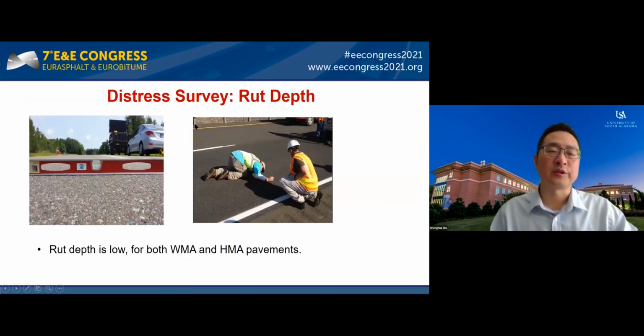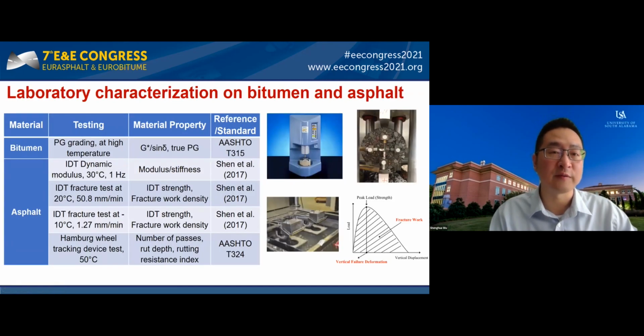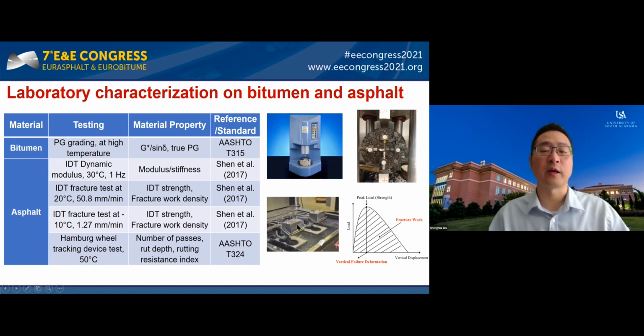The third major distress we find is the rutting depth, but we find that the rutting depth is very low for both WMA and HMA pavements. So besides the distress survey, we also collect a lot of field cores for each pavement section. We do the binder extraction. We also do a lot of testing on the bitumen in terms of PG grading, G-star over sine delta, etc. For the asphalt mixture cores, we run the IDT modulus. We also run the IDT fracture testing at room temperature and low temperature, one at 20 Celsius degrees, one at negative 10 Celsius degrees. We also did Hamburg wheel tracking device testing on the field cores, and Hamburg wheel tracking testing can also provide us the moisture damage resistance of the asphalt mixture.